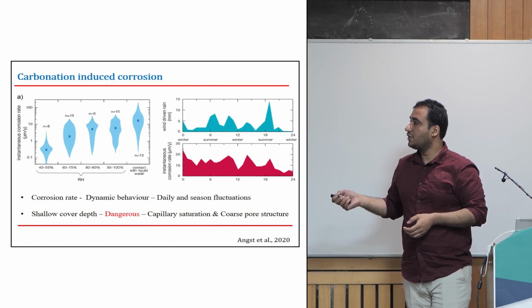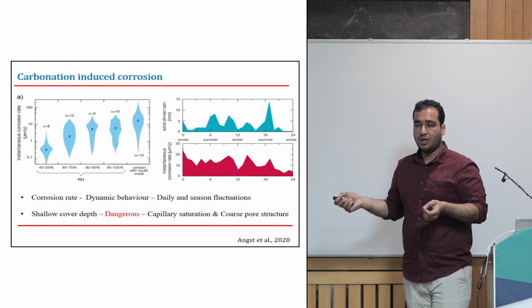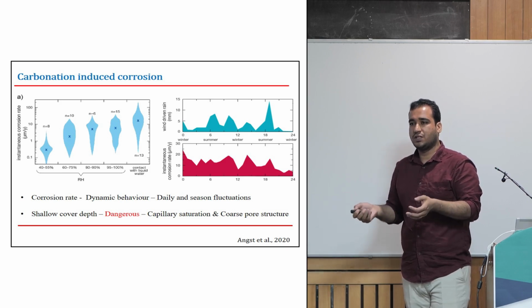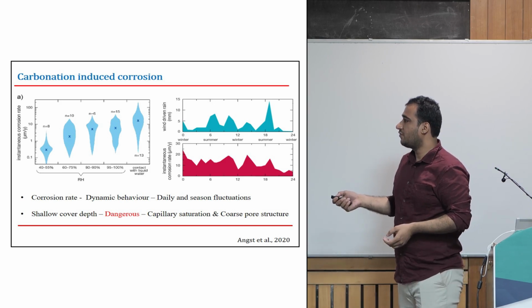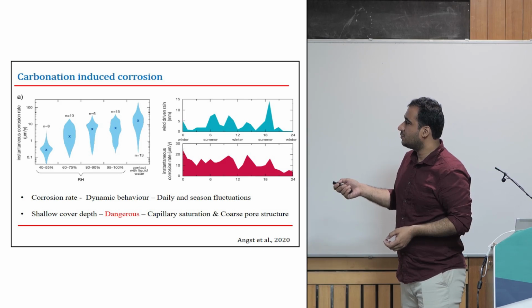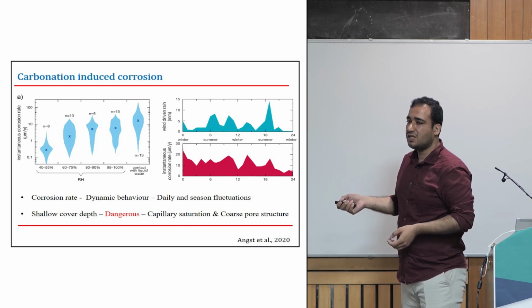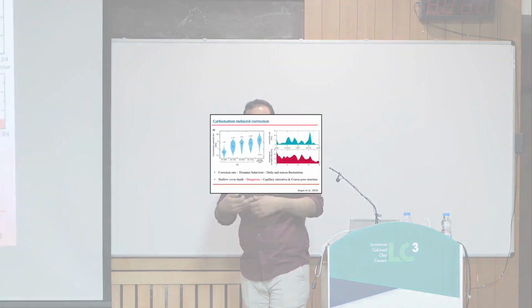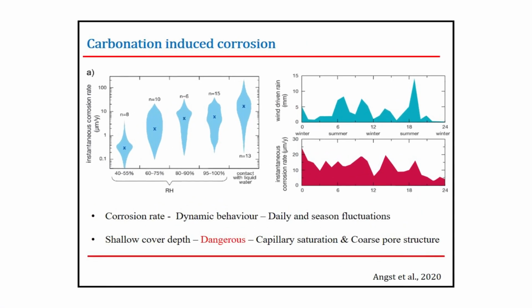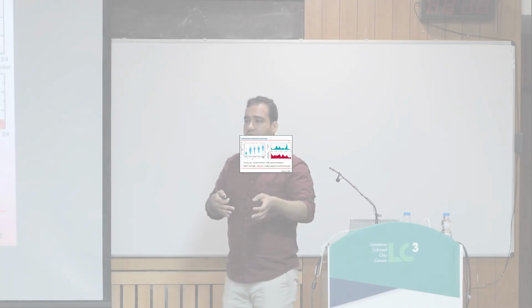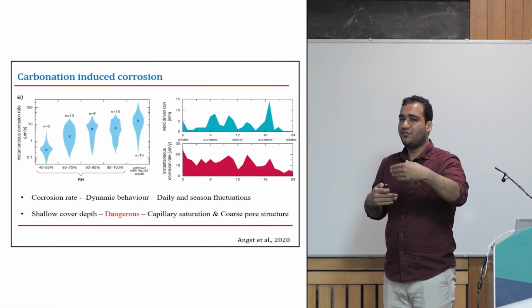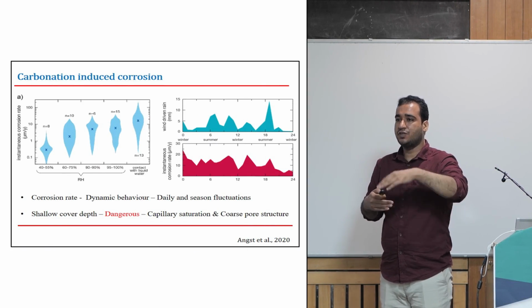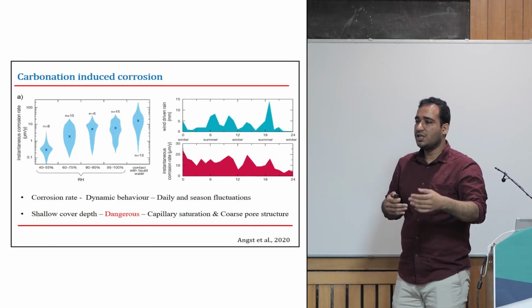The corrosion rate will be high when the relative humidity is quite high. But we all know our structures are not always wet, especially the ones we are living in commonly here. Since they are not wet, they are subjected to wetting and drying cycles. It's your daily and seasonal fluctuations. If you get a rain spell or if you splash some water, you see a spike in the corrosion rate, but when it's dry, it again comes down. So it's a dynamic process. It's continuously fluctuating. So often we study at extreme conditions of corrosion rate. We can't directly extrapolate that into the field. We have to consider that the variation of the daily relative humidity and saturation level is going to affect our structures.